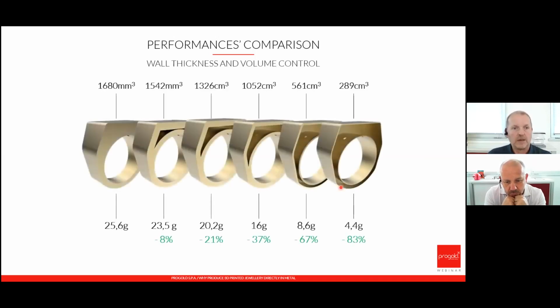Here, wall thickness and volume control. We say that SLM allows you to create large and flashy hollow objects. At the drawing phase, you can choose the wall thickness that you need and so decide the volume and weight of your parts. Here is an example of the same external dimensions for these parts and a completely different volume and weight, according to the dimension of the wall thickness.